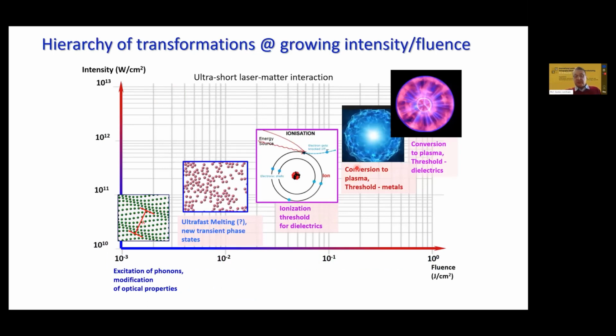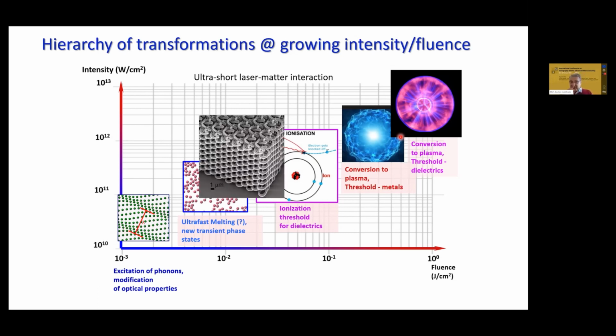So the set of conditions which we can reach with quite simple tabletop lasers, here it's fluence, and because pulses are very short, intensity has very high values here. So we can start with small pulse energy, small fluence, then we can have simply heating of material, and then we can drive it to melting, evaporation, ionization, and going into plasma. So these are all phase transitions, which you can actually cover with 3 orders of magnitude in fluence and intensity. So very popular 3D laser writing for polymerization actually is happening somewhere in this range, around 1 terawatt per square centimeter. So it's high intensity, which is already making ionization of materials. So it means you are generating electrons when you are modifying your materials.